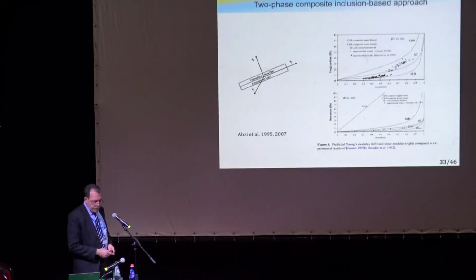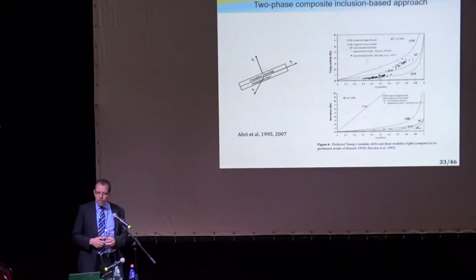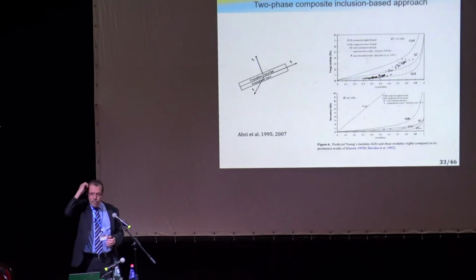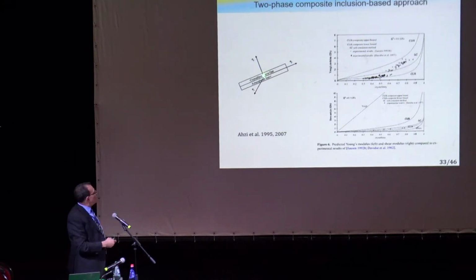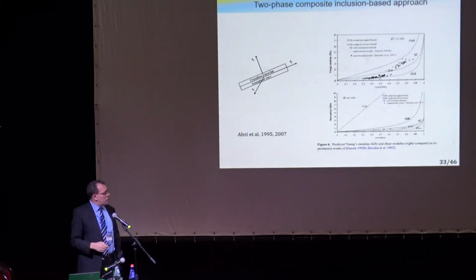But in 1995 and later in 2007, I developed this two-phase inclusion model, which is like a lamella, but with two phases, with a planar interface, and it just imposes the planar interface jump conditions at this interface, and I used it as my inclusion. I developed a composite upper bound based on this inclusion, a composite lower bound, and the classical upper bound will be here, the classical lower bound will be here. And then based on this inclusion, a self-consistent model. And these are the results we got, very nice results actually with this simple model.